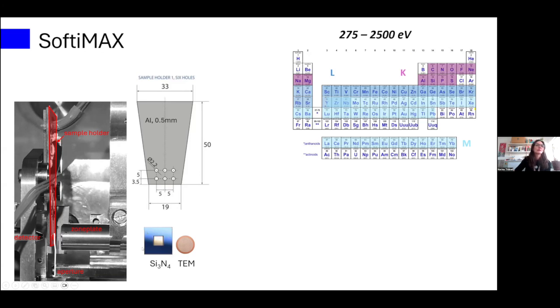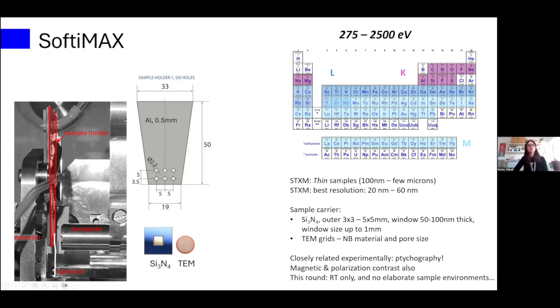They can be either 5 by 5 or 3 by 3 in this outer region, and the window size up to 1 by 1 millimeter in size, or TEM grids. And then with that, we can say thin samples is the norm, as said. Soft X-ray, everything is very close as well. So typically 100 nanometers or around this is used for the lower energy, so the carbon, for instance, and you can go up to a couple of microns when you get to the higher energy side of the beamlines,